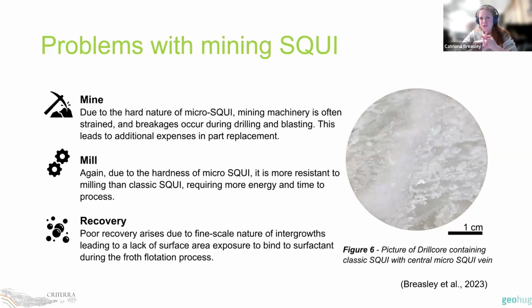So micro-SQUI, as I previously mentioned, is incredibly hard, very intergrown with quartz, a very micro scale feature, and this leads to three main issues. The first, during mining. When I'm at Tanco, the underground miners always tell me that they know they've hit a face of micro-SQUI because all of their machines start breaking underground. So due to this very hard nature, machines break, strainages occur during drilling and blasting, and this leads to additional expenses and part replacement. In the mill phase, micro-SQUI is very, very hard, so it's more resistant and energy intensive, and it takes a lot of time to process, and it often has to be reground multiple times so you can actually liberate the lithium.